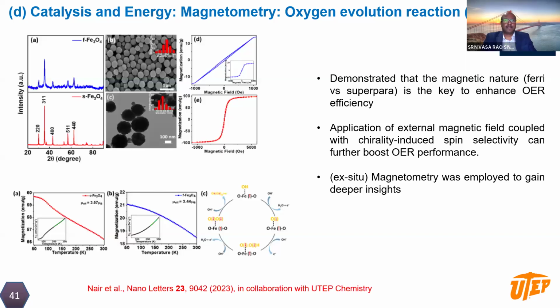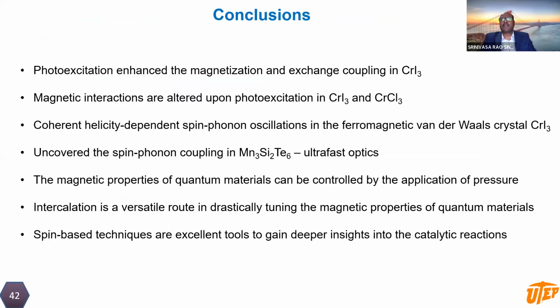Similarly, on our campus, the chemistry department faculty have been working with iron oxide materials for the oxygen evolution reaction. They took two independent iron oxide compounds, and one iron oxide compound showed much superior oxygen evolution reaction compared to the other. They approached us, and we used our expertise in magnetism, and we found that one compound has higher spin polarization compared to the other. Using those measurements, coupled with their own measurements, they constructed a mechanism for why these iron oxide compounds show superior oxygen evolution reaction. And that established the fact that one can employ spin probes to detect energy reactions while they're taking place. So there I conclude my presentation.